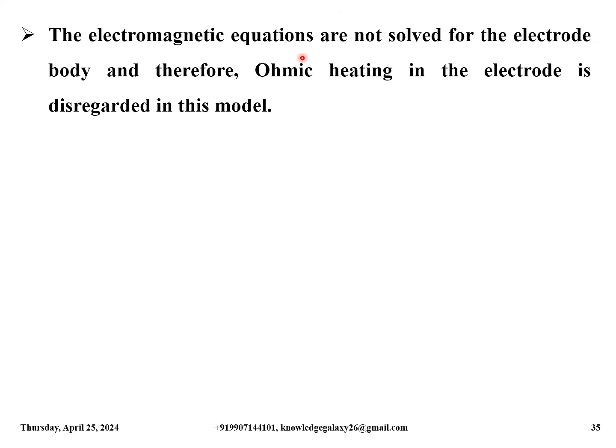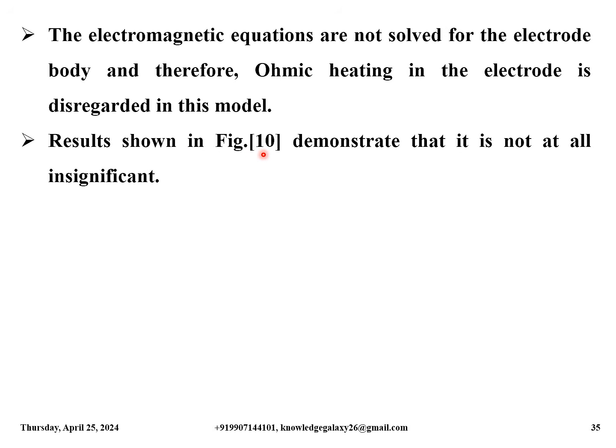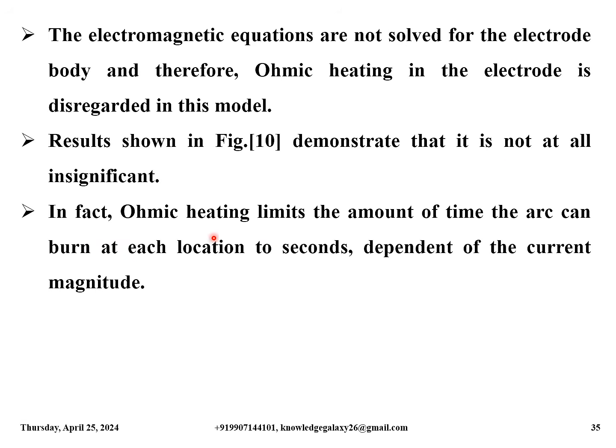The electromagnetic equations are not solved for the electrode body and therefore ohmic heating in the electrode is disregarded in this model. Results shown in figure 10, which are coming in the next slides, demonstrate that it is not at all insignificant. In fact, ohmic heating limits the amount of time the arc can burn at each location to seconds, dependent on the current magnitude. For the cathode spot behavior, while the arc is at a certain location, the ohmic heating within the electrode is, however, insignificant.